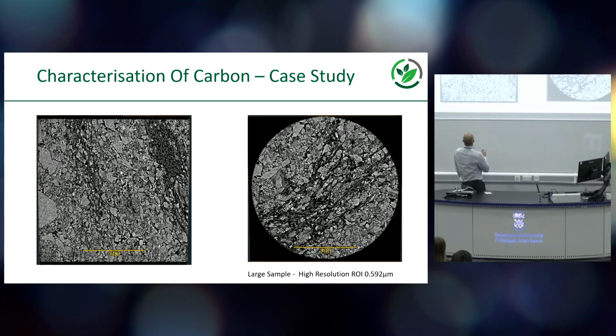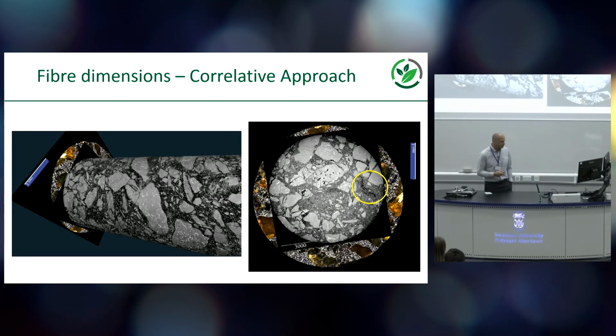And we've basically probed the limitations of the technique. So these are non-destructive images. So these are slices made up from 3D tomography. And you can see here hints of individual fibres through the structure, and also large areas of fibres potentially all clumped together. But in terms of actually resolving the size, shape, form, length of those individual fibres, which we were actually tasked to do, we found that really, really difficult.